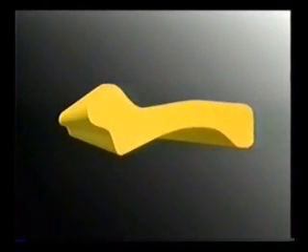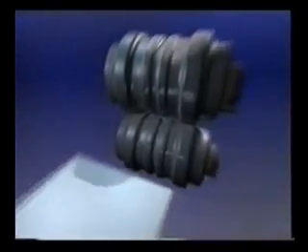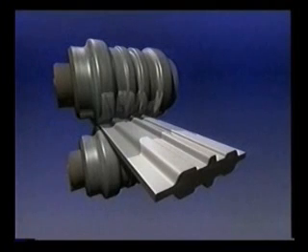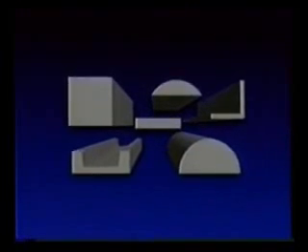22 rolls, 11 sets of 2 rolls, precision machined in progressive configurations, form the semi-finished steel billet into an asymmetrical near-net shape. The billet passes through only one set of rolls at a time, allowing it to elongate on one side faster than on the other, thus accommodating an odd or unbalanced shape. This unique feature of McDonald Steel's shape mills sets them apart from other merchant bar mills, which can only roll symmetrical shapes such as rounds, squares, angles, channels, and flats.